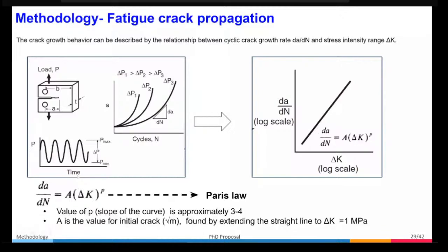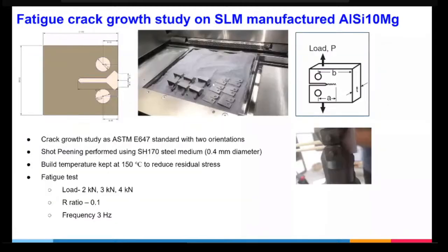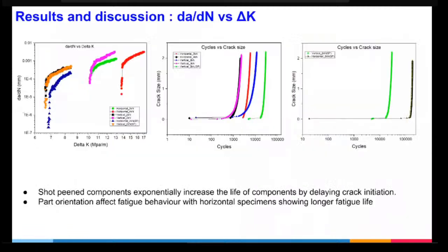Now this is how we actually print the component. This is called CT specimens. So once you see here, we printed components horizontally, vertically, and all those things, and we subject this component under fluctuating load, and we actually measure how the crack is propagating with respect to delta K value. And very interestingly, you can see that the samples which are printed horizontally show a lesser amount of crack propagation, which is quite interesting.